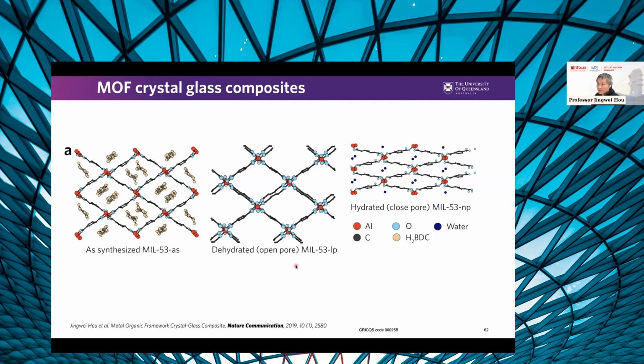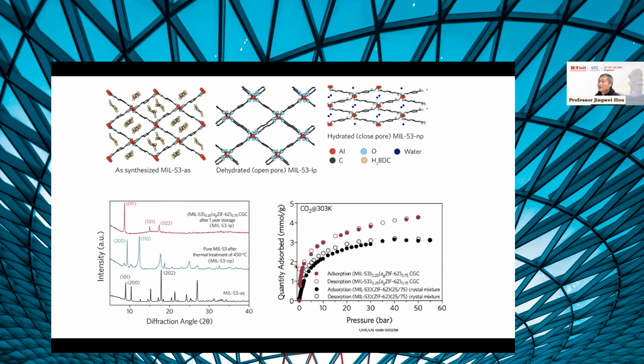The synthesized MOF contains the ligand and the solvent, so it stays in the large pore phase, but it's filled with all types of things. We have to activate the MOF with high temperature, becoming large pore phase, but this phase is not stable. So cooling back to room temperature will lead to a small pore phase. That's not a good thing for us.